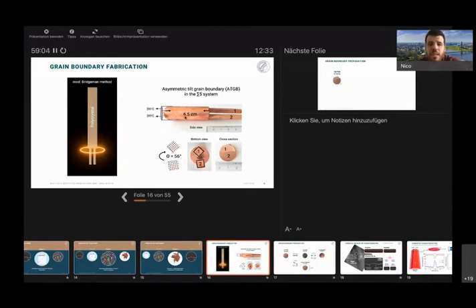So this one functioned very nicely because the growth directions of both crystals are the same. That means it's not very different how the crystal grows. It does the same on both sides, so the grain boundary does more or less stay straight. We also grow grain boundaries in this way, where we had two very different growth directions.